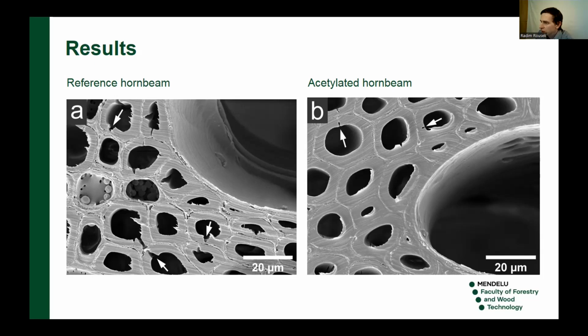And the other difference between reference and acetylated hornbeam are these pits. The pits are shown with these arrows. These white arrows show the pits in reference on the left and acetylated hornbeam on the right side. And you can see there is a big difference between the pits. Reference hornbeam has very wide pits due to cell wall shrinkage. And acetylated hornbeam has the pits very narrow. It's due to swelling of the cell wall during acetylation process. So the cell wall is permanently swollen and the pits are slightly closed.